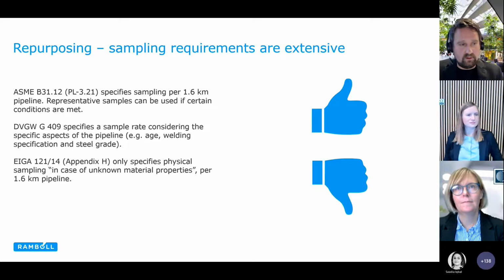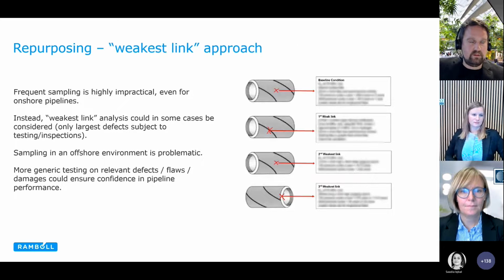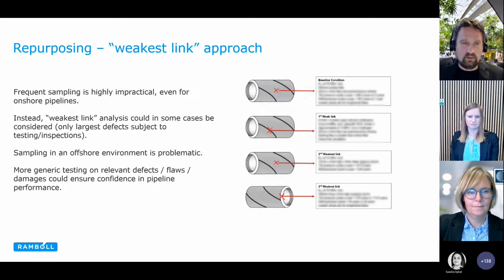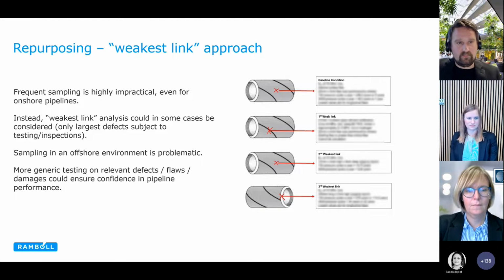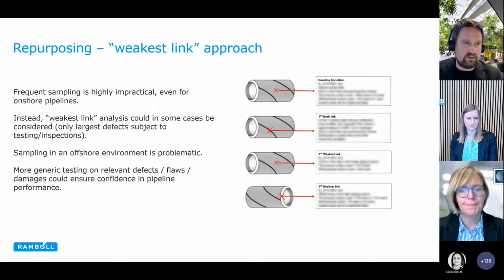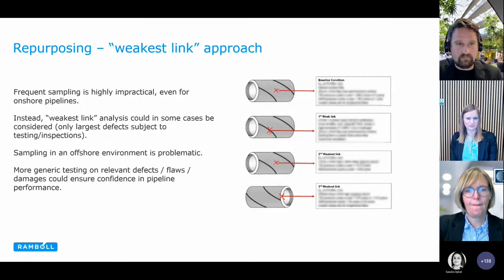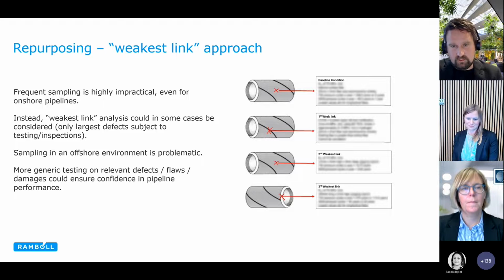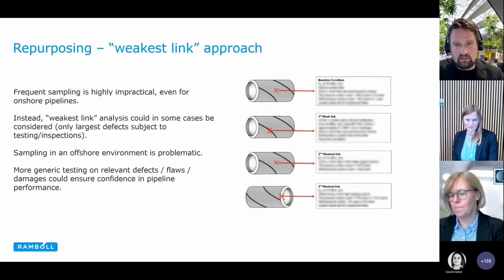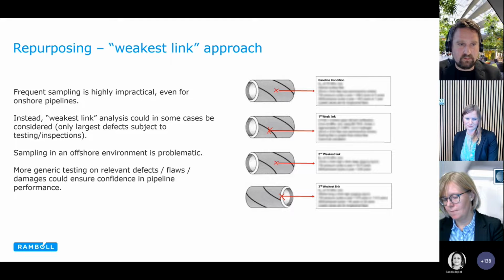So another approach, and this is something we did together with Force Technology for a study, is to do a weakest link analysis, where we go through the inspection records. We identify what we saw as the major flaws and defects, and even do an evaluation on some sort of standard defect, just a conservative standard defect, and then calculate for a particular number of pressure cycles at a particular level to calculate the lifetime of this pipeline. And we think this would be a more targeted approach for a specific pipeline than doing extensive sampling, which potentially induces a lot of harm for the pipeline.